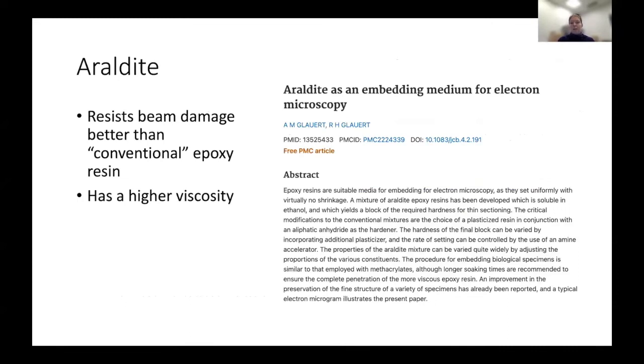Araldite is a more viscous resin. It resists being damaged better than the conventional epoxy. It has a higher viscosity, so it doesn't infiltrate samples quite as readily. It's also colorless. EPON is a bit yellow when it's cured. I mean, it could range from yellow to orange based on the amount of accelerant you use in your recipe. But Araldite is colorless, which is nice if you're doing correlative light and electron microscopy or something to consider.